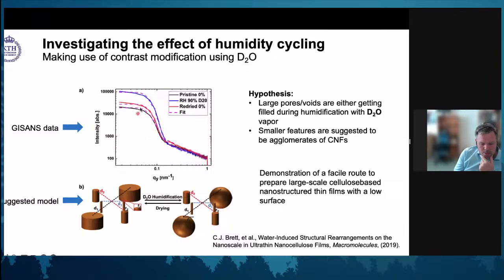What we can see is that we're changing the intensity when we humidify. So we go from the black to the blue. And when we re-dry, we never get back to the original film. So two things happen. First of all, the structure we get when we put in water changes morphology. And the second part is that by cycling this, we can see that the humidification permanently introduces changes to the original structure of the film. So that is possible by using neutrons.